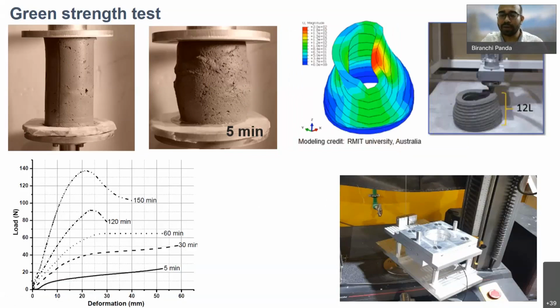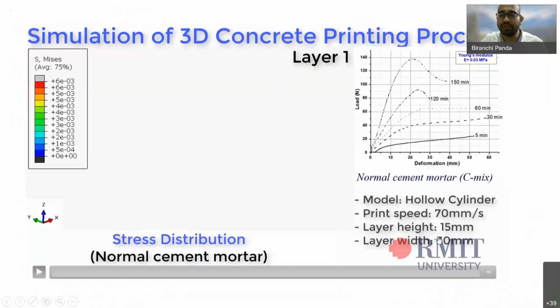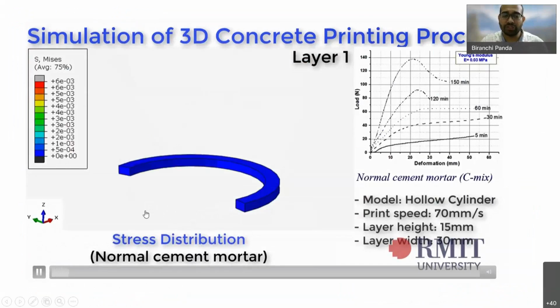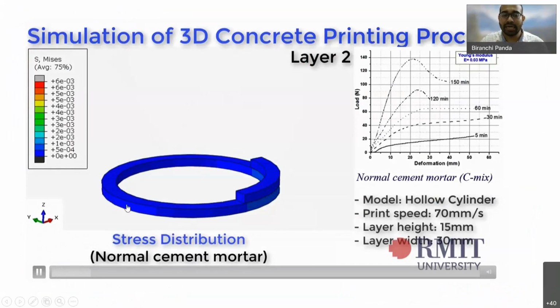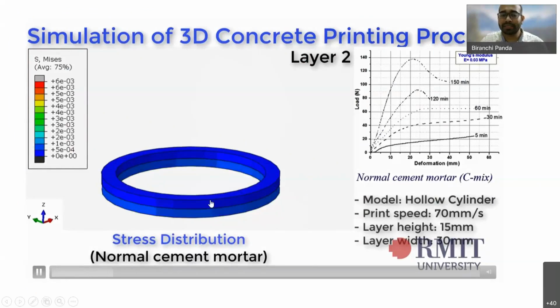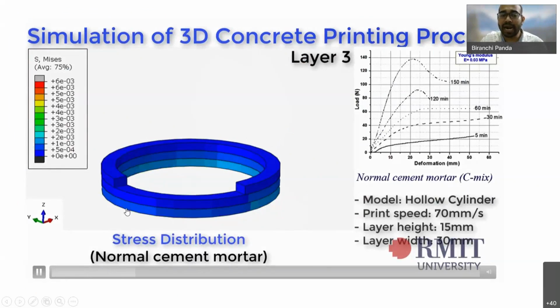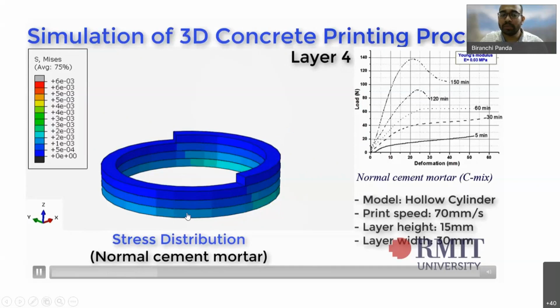Okay, so this collaboration we have done with RMIT University Australia. They have used the experimental data to model the entire printing process. I hope you can see that they are trying to deposit the layers virtually, and they are seeing the maximum stress that is occurring on the bottom layer. This model incorporates the time dependent property of the material, so that if the material is hardening at a very fast rate, you won't see any stress on the bottom layer.